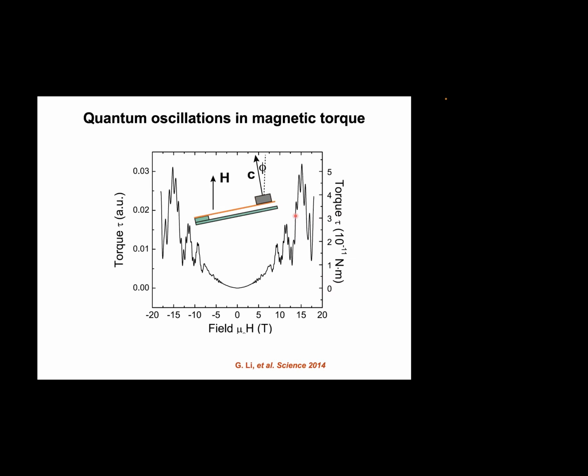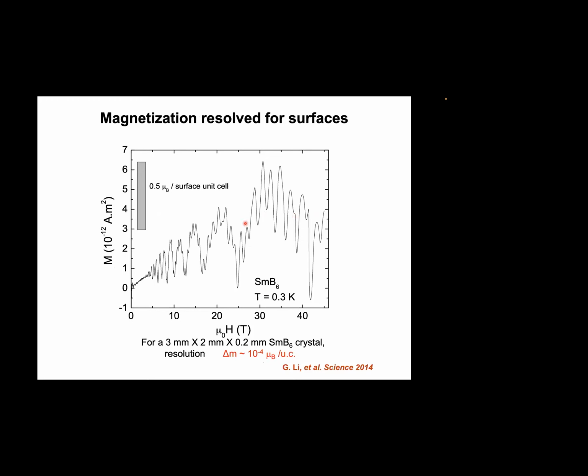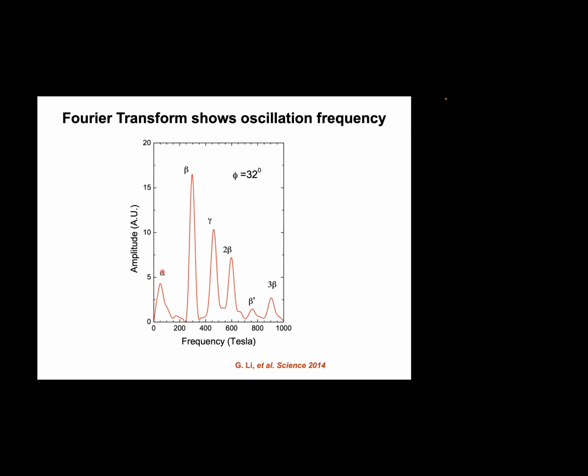Now, that's magnetic torque. We divide the torque by H to get our effective magnetization. This is data we present all the way up to 45 Tesla. At low fields, again, we have this linear dependence, nothing surprising. This is a paramagnet. As we go to stronger fields, we have slow oscillations, fast oscillations, or beating patterns. That means we should have at least 3 primary frequencies. And indeed, we have 3 primary frequencies as we carry out Fourier analysis to find the oscillation frequencies.